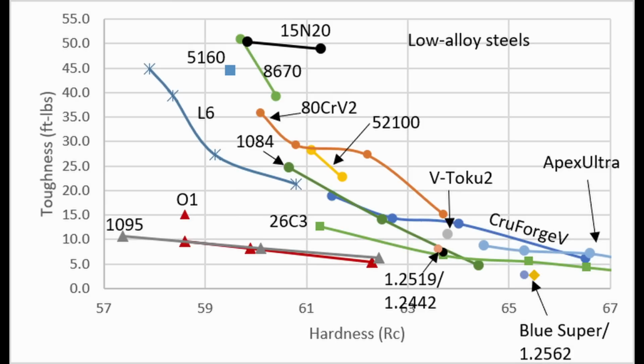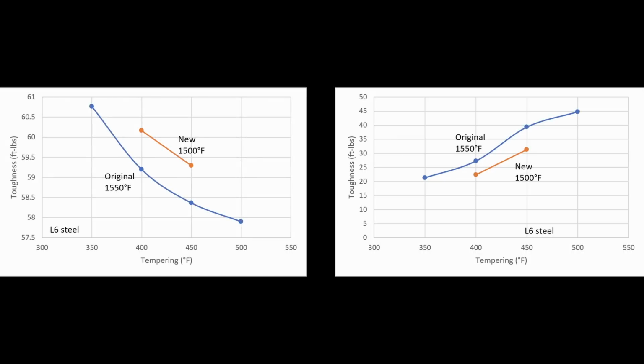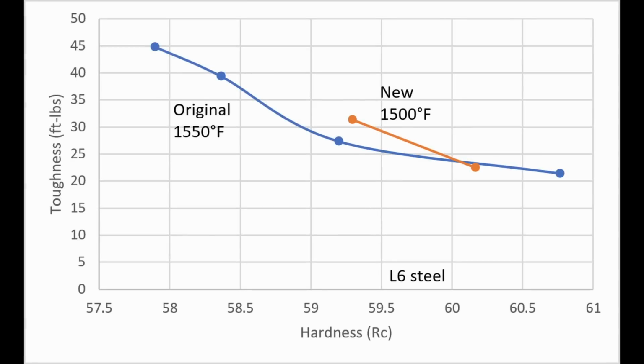If I get some other L6, maybe from a different source, like we get the Moly version, for example, I would be interested to see how that tested, if it does as well as 15 and 20. But for now, this is the result that we have. The L6 tests very well for toughness, but not stellar like the 15 and 20 did. Now, my heat treatment did result in a little bit higher hardness, probably because the annealed microstructure I developed thermal cycling was finer than from the factory. But that higher hardness was also offset by somewhat reduced toughness, which means that in the end it balanced out and they were about the same when it comes to hardness, toughness, balance.